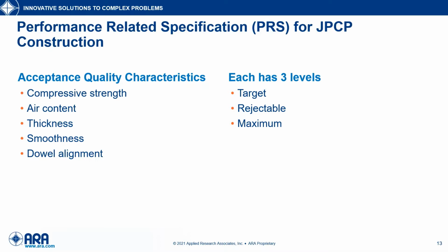So for that pavement, we had 5 acceptance quality characteristics in the tollway specification. So this included compressive strength, air content, concrete thickness, surface smoothness, dowel bar alignment, and each of these acceptance quality characteristics had 3 levels, a target level, a rejectable level, and a maximum quality level.